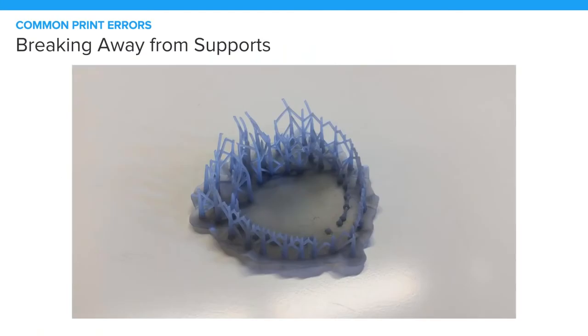So breaking away from supports is another very common issue that we see. It occurs when a model is improperly or under-supported or when the touch points are too small. So if you've adjusted any of the default settings, you should try and go back and reset it to the normal size. Typically, I think the default is 1. Actually, yes, it is 1. You really shouldn't vary from that too much unless you have a specific issue. So unless you're getting non-adherence, you could increase it slightly, or unless you're getting just too many supports on the part, you can decrease it slightly.